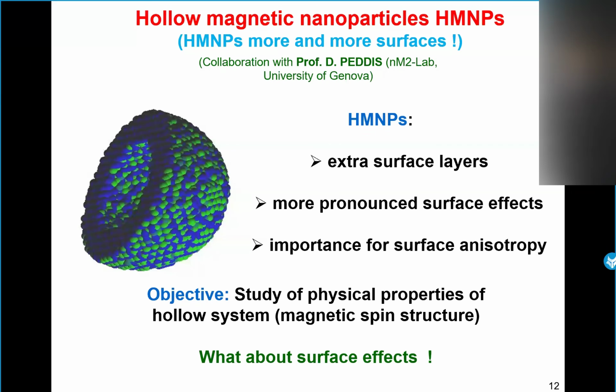Now if we change the morphology of the magnetic nanoparticles, hollow magnetic nanoparticles are an ideal system to study the surface effect because of the presence of extra surface layers. So we have a more pronounced surface effect and more importance of surface anisotropy. In magnetic nanostructures, the contribution of surface anisotropy and surface effect to the physical properties is not well understood. Any unexpected behavior, we attribute to surface effect. But this system is formed just from the external and internal surface, and we hope that we arrive to understand the physical properties and the contribution of the surface effect in this system.